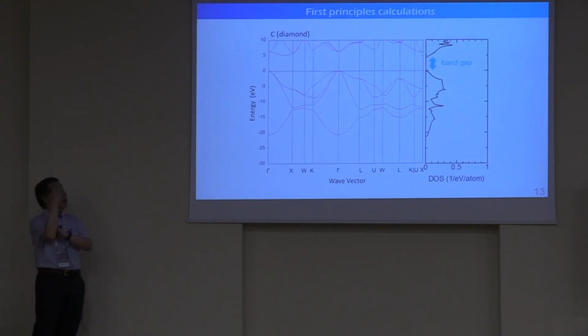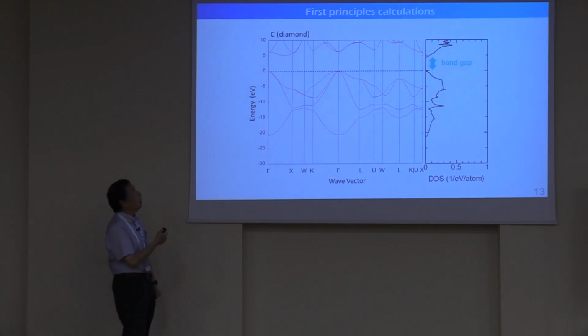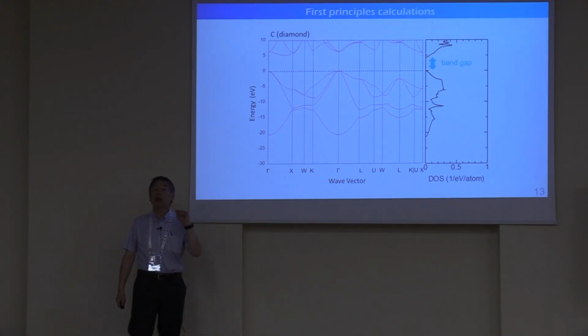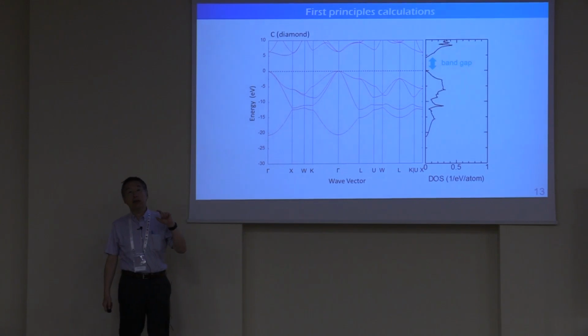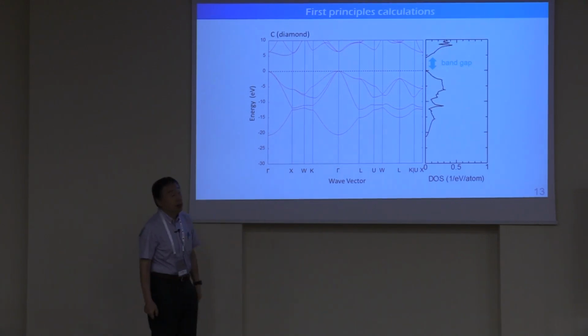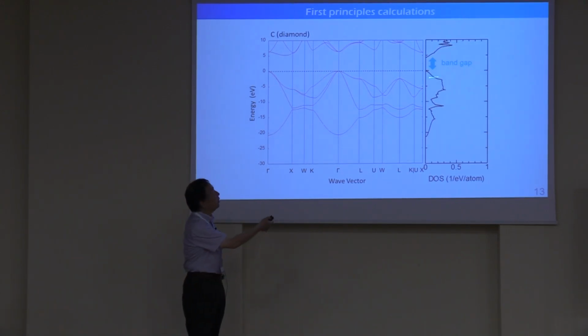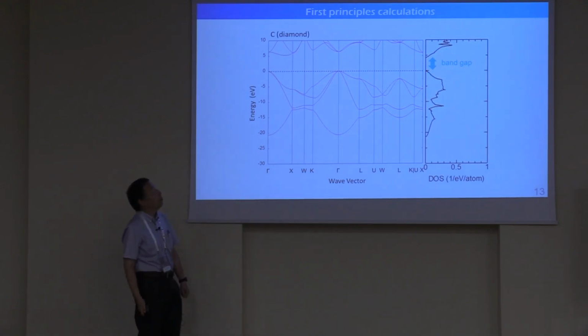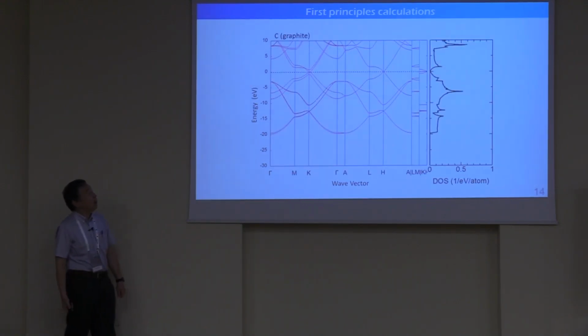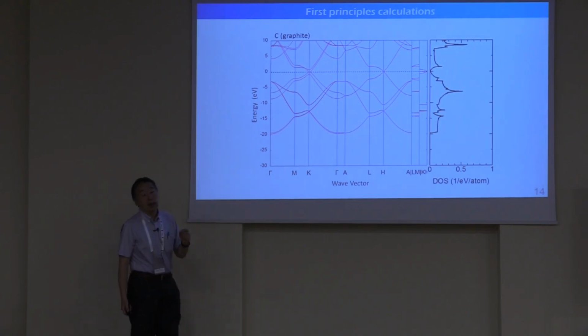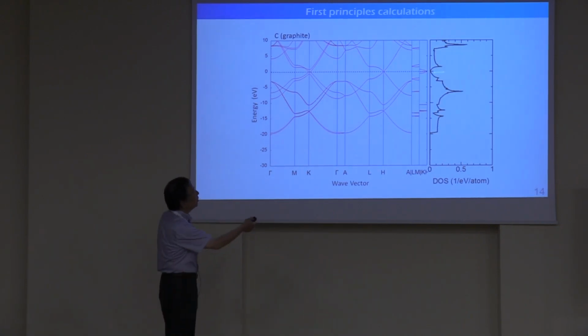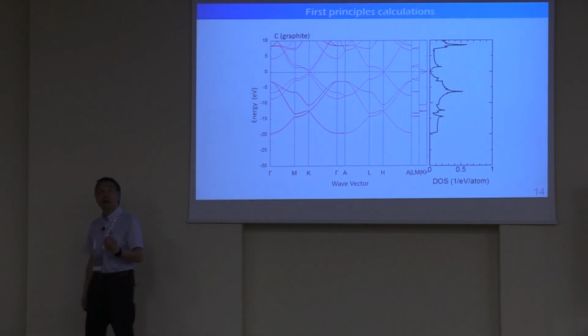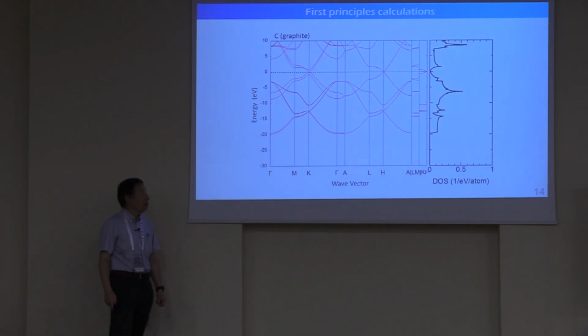But this is again the one structure of diamond, and from the transparency you can guess that it is insulating. So you can find here a band gap, clear band gap. But in the case of graphite, it is electrically conductive, so there is no band gap. Actually, the density of states here is very small, but it is finite. So it has electric conductivity.